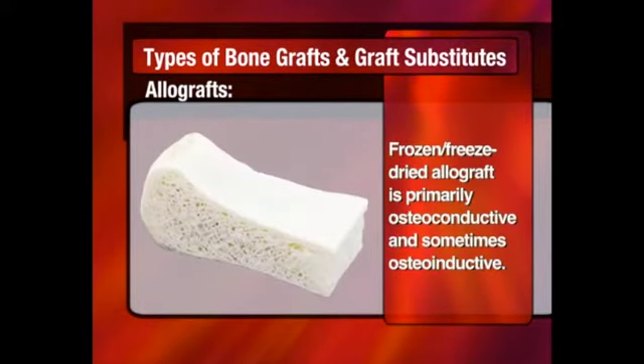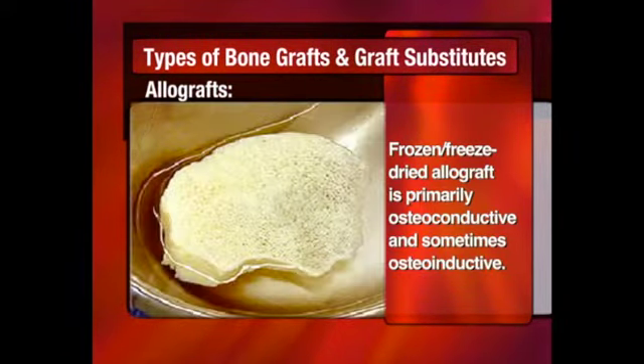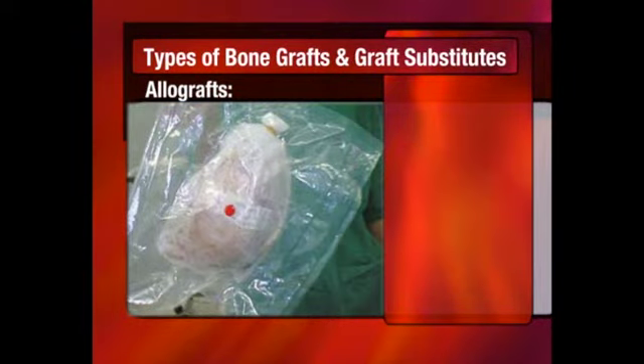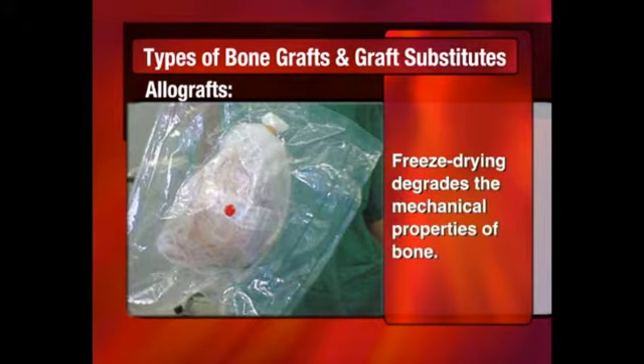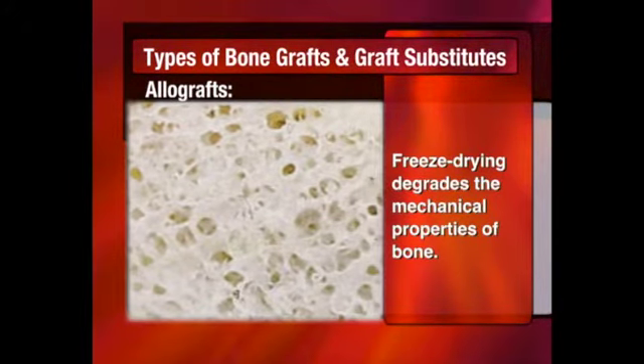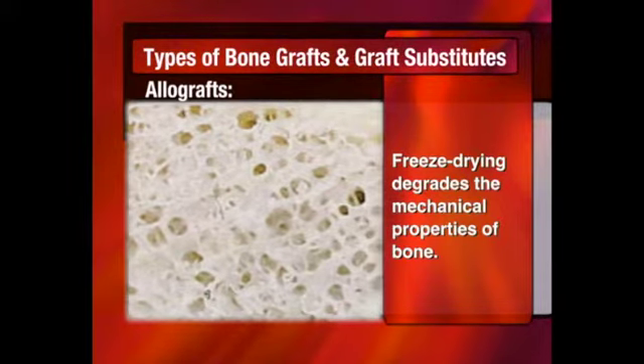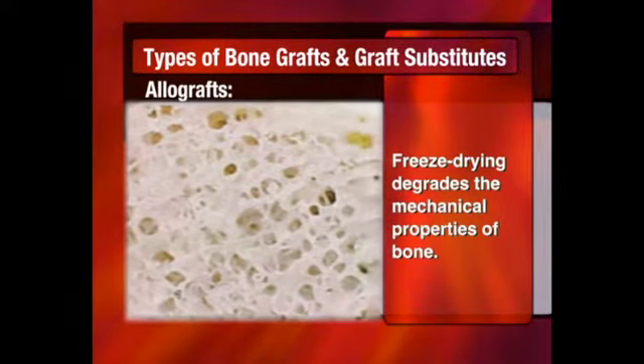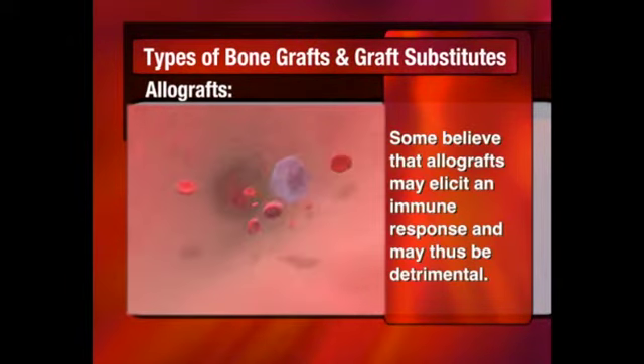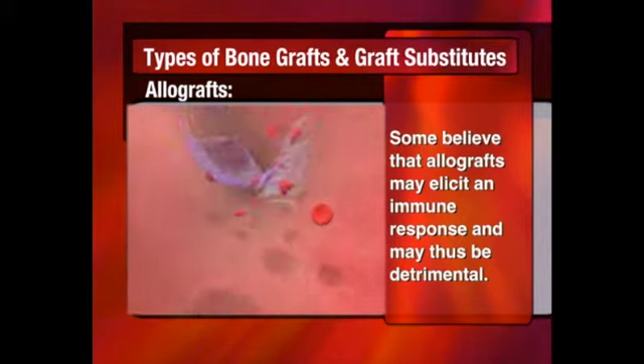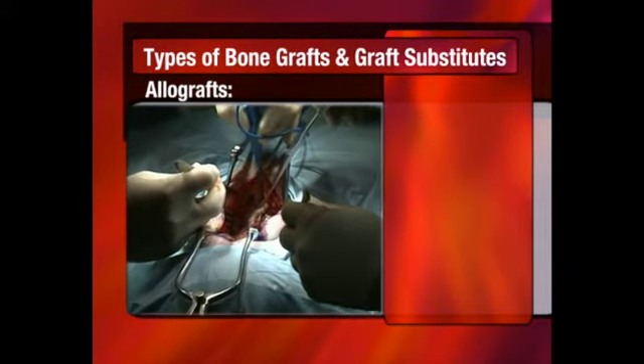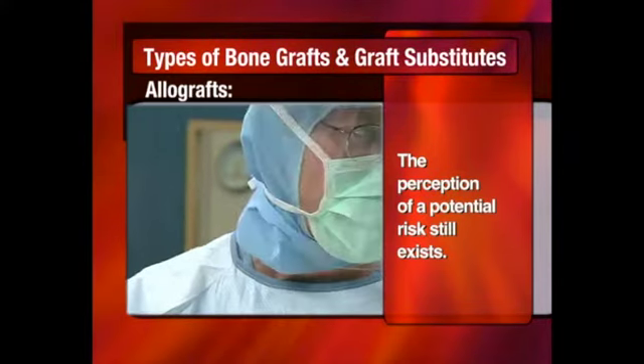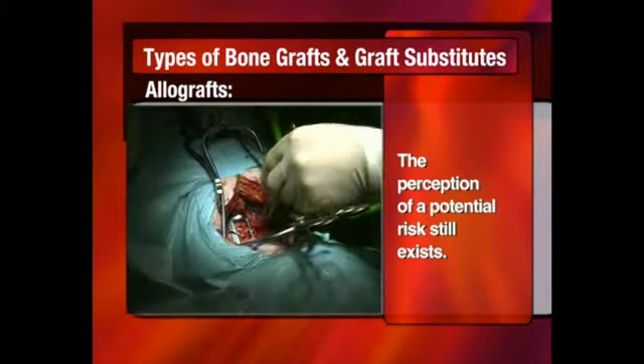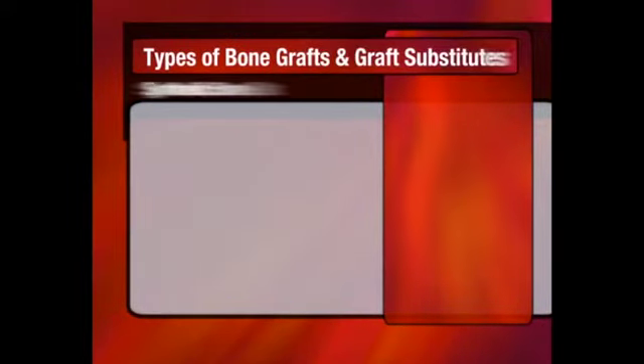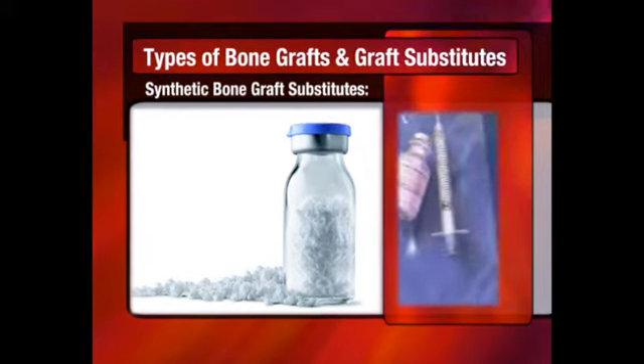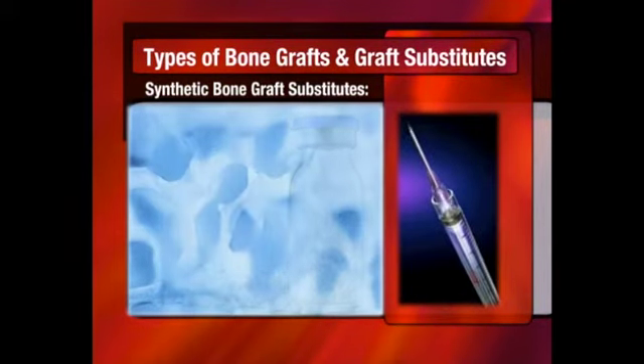Frozen or freeze-dried allograft bone is primarily osteoconductive and sometimes osteoinductive. Frozen grafts are preferred over freeze-dried bones because the freeze-drying process degrades the mechanical properties of bone, further limiting its application in situations where structural support is needed. Finally, some believe that allografts may elicit an immune response and thus be detrimental. In addition, while today's allografts are processed to eliminate most risks of disease transmission, the perception of a potential risk still exists.